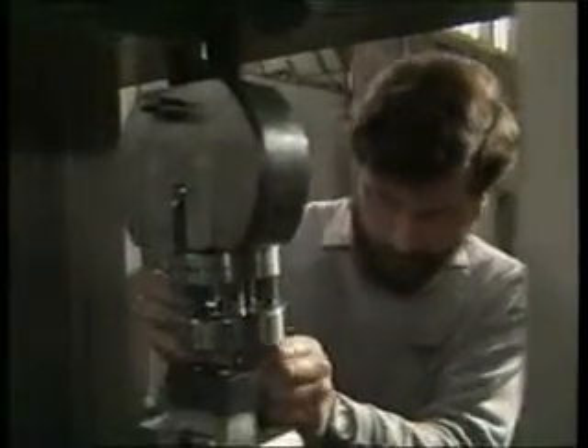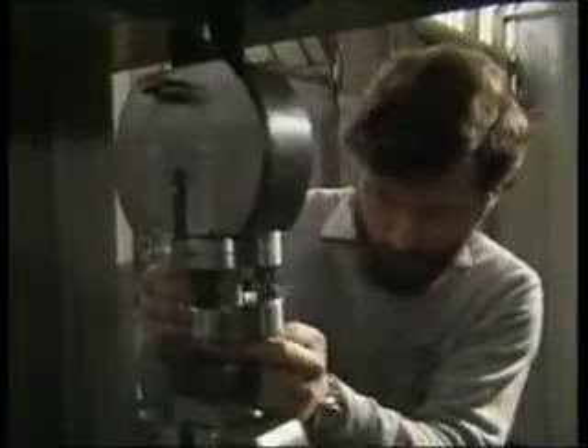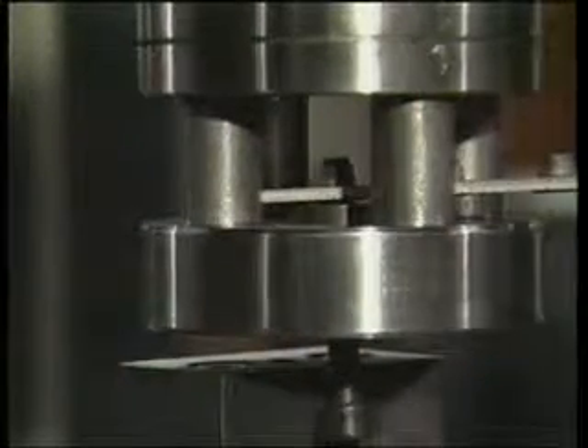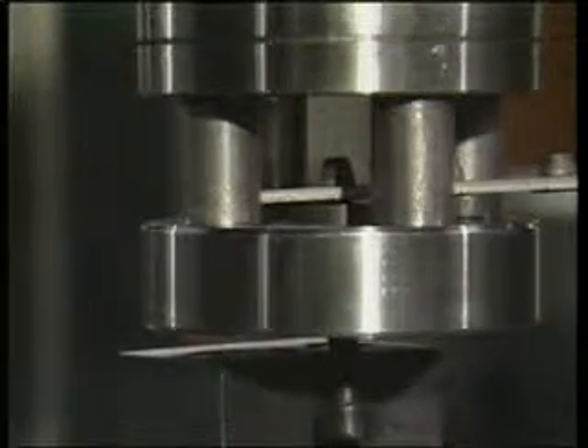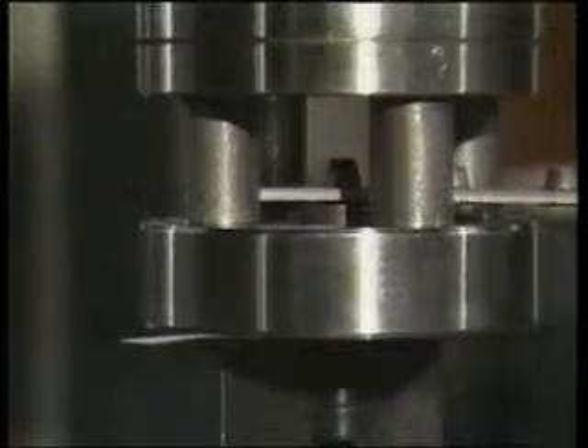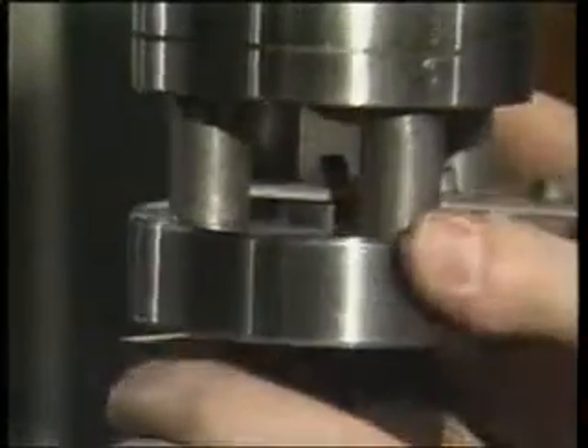Thread strength of a cold-formed tapped bushing is tested in this example. It involves 11-gauge mild steel tapped for an 8mm screw. Tensile strength of the screw is almost 9,700 pounds. Minimum acceptable tensile strength of the threads is about 5,350 pounds, according to German standard 267.11.